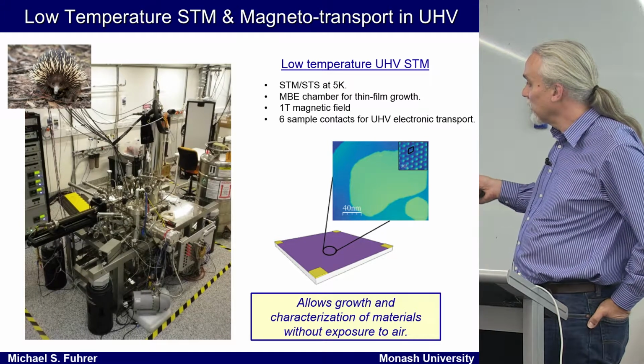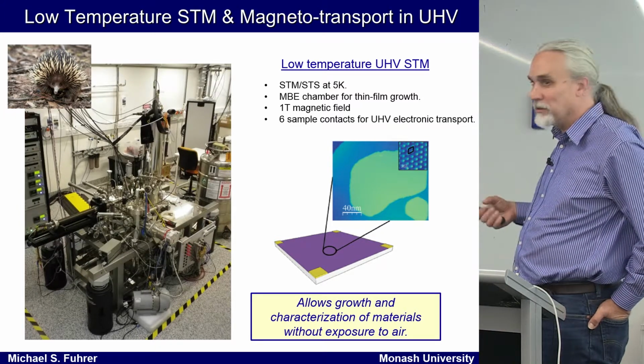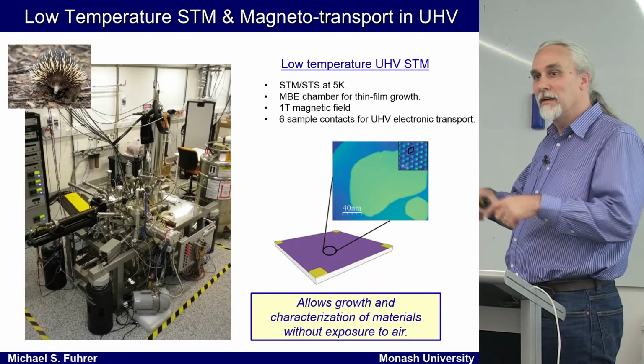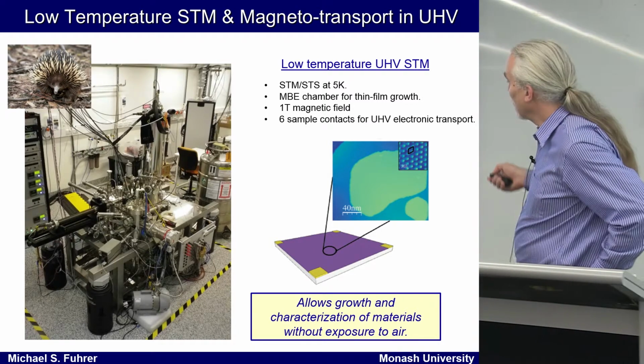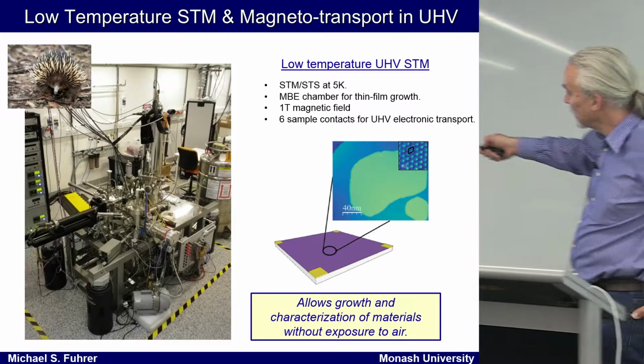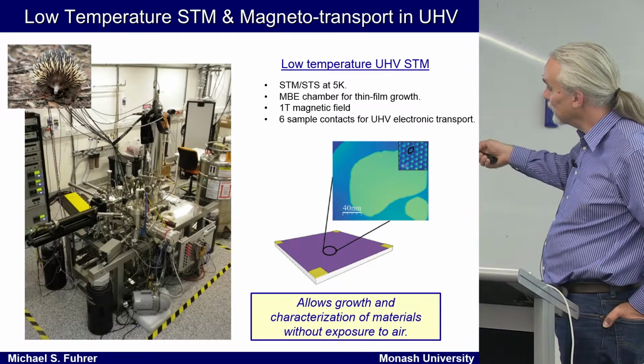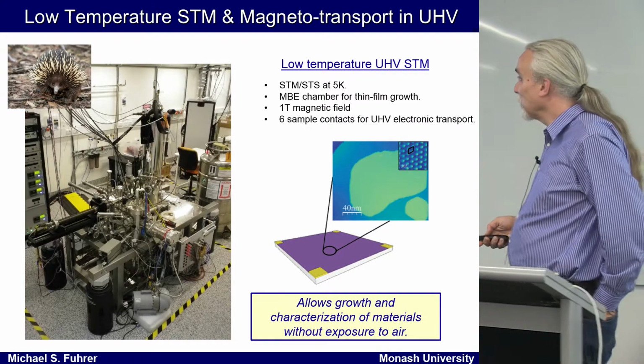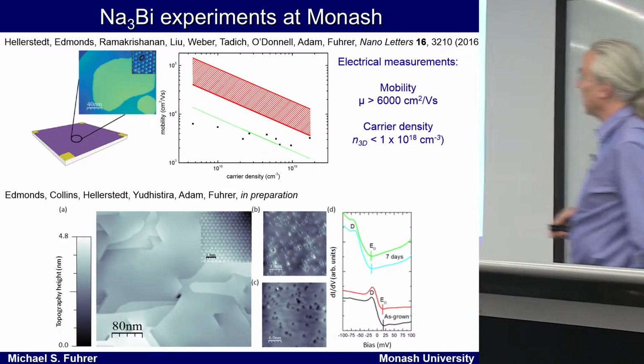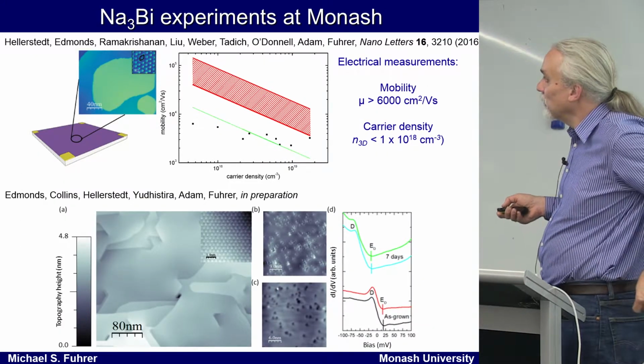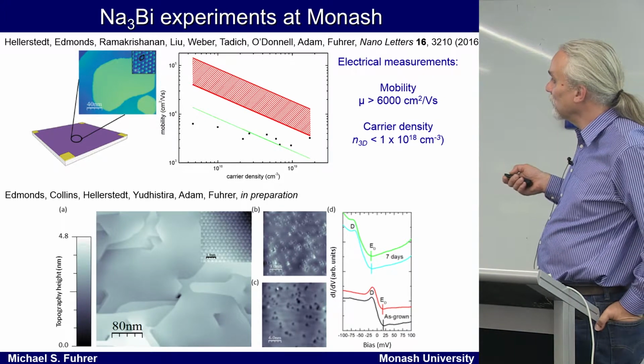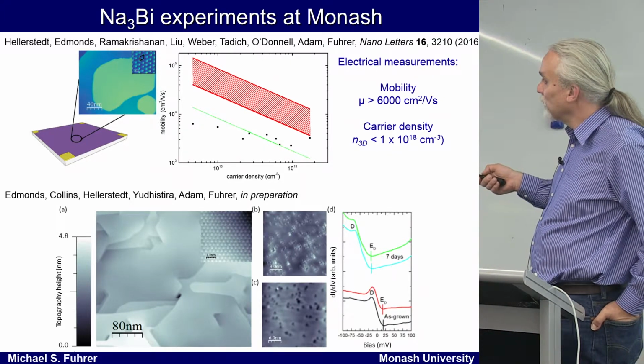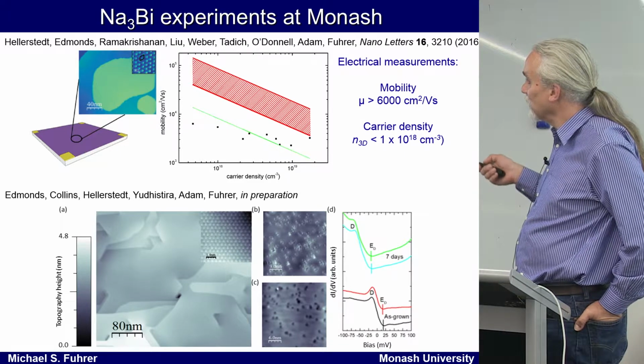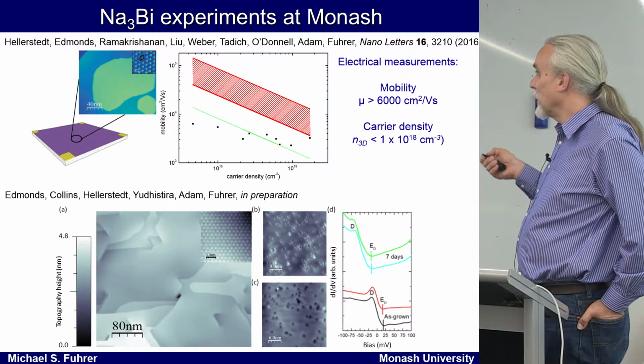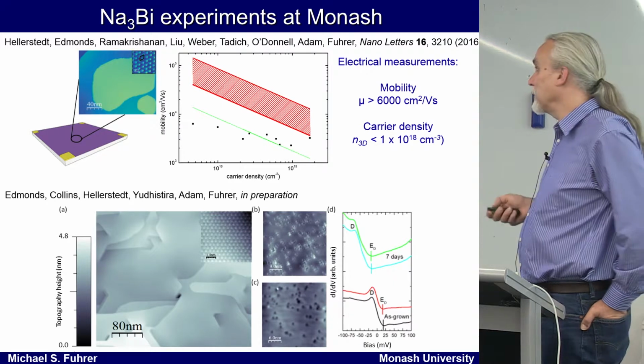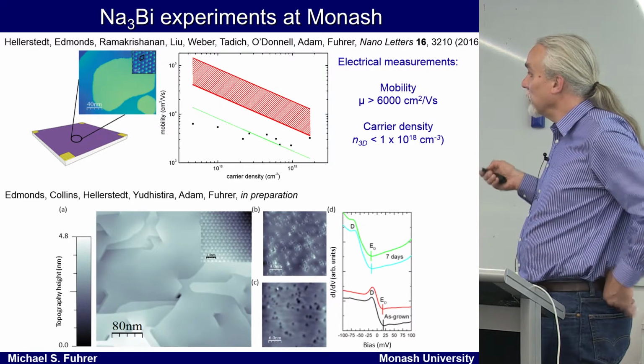So these materials are actually grown on pre-existing electrodes on insulating substrates that are all wired up to do electrical measurements, and we can go in with the STM and image. These are sort of atomically flat terraces of this material, and these are the atoms with an STM. And I'll just show you a couple of results that have recently come out. So we've been able to make this material and measure its mobility for different samples with different carrier density. We get really nice mobility. This is about where people started with graphene at 6,000 centimeters squared per volt second, and pretty low carrier density.